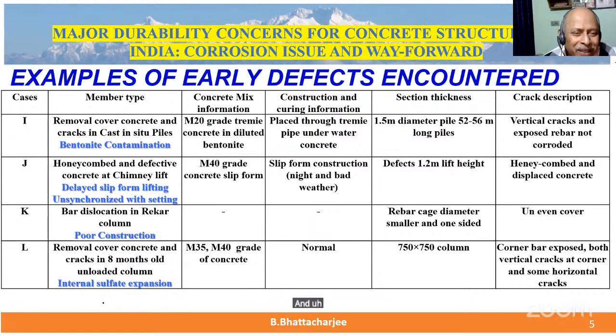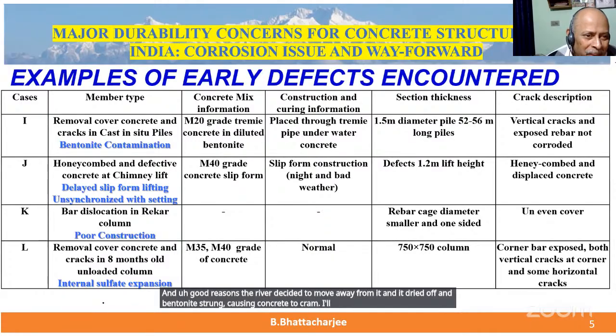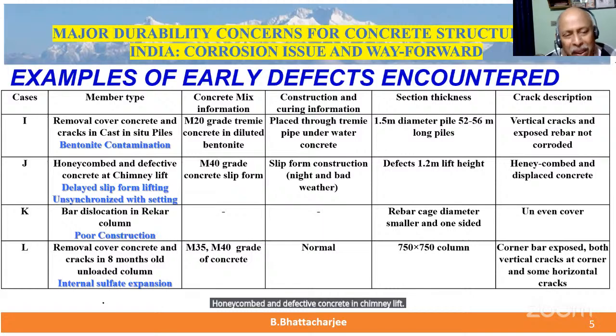So here what happened is bentonite contaminated the surface concrete because it was not diluted sufficiently. And for good reasons, the water decided to move away from it and it dried off and the bentonite shrunk, causing the concrete to crack. I'll show you that anyway. Honeycombed and defective concrete in chimney lift. I have seen a number of them actually.